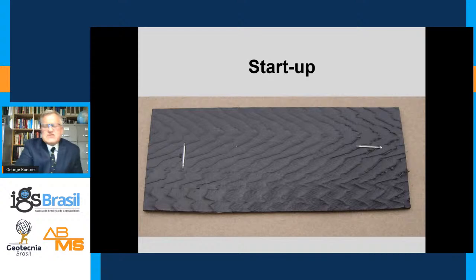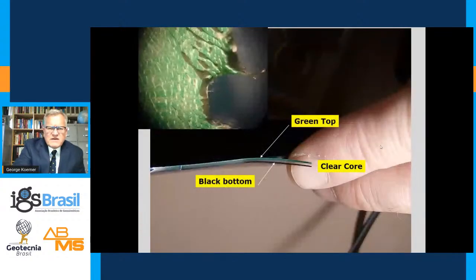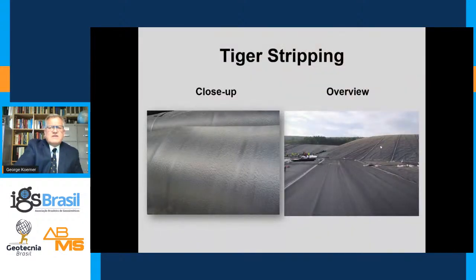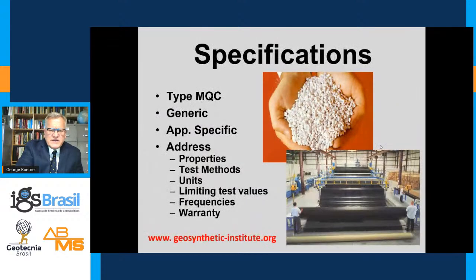You also have startup runs, which are between different materials, changing over from linear low density to high density, or changing in thickness. There could be startup issues. You don't want this material on your site. There could be problems with AO packages, which are found out in long-term problems. There could be problems with inconsistency or tiger striping of the material. Certainly, you didn't pay for this. This was not the material shipped for direct shear testing, and certainly is problematic and should be avoided.